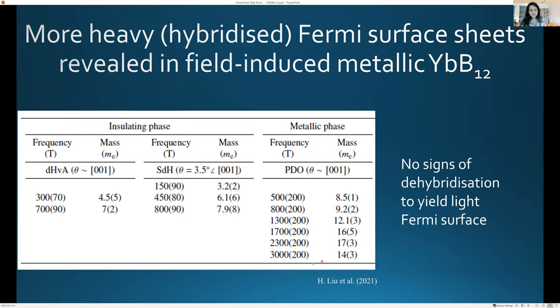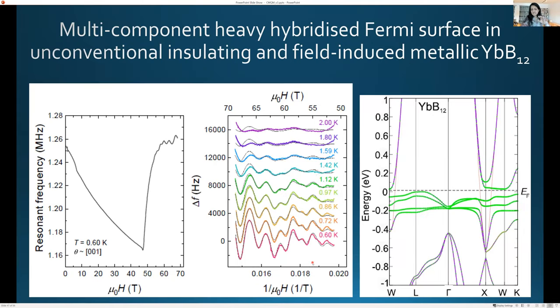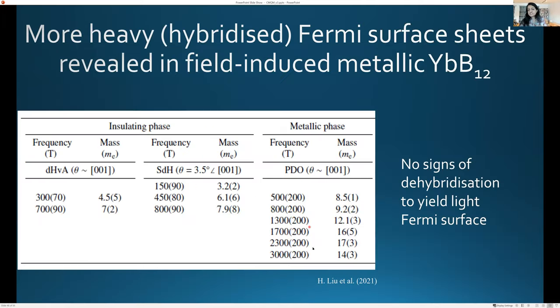The reason being that the heat capacity actually increases when we go into the metallic state. So gamma grows as we go from the insulator to a metal, implying that we have acquired new Fermi surface sheets that are still hybridized as you go into the metallic state.